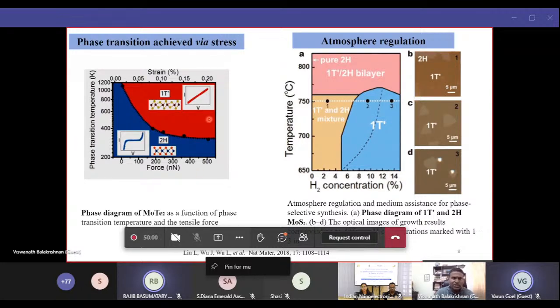In terms of phase engineering, there are reports we can stabilize the 1T prime or 1T phases by applying stress. In this case, it is done with a force. With a high amount of either strain or stress, you will be able to stabilize the 1T prime phase. In CVD growth, it is also possible to stabilize this 1T prime phase.